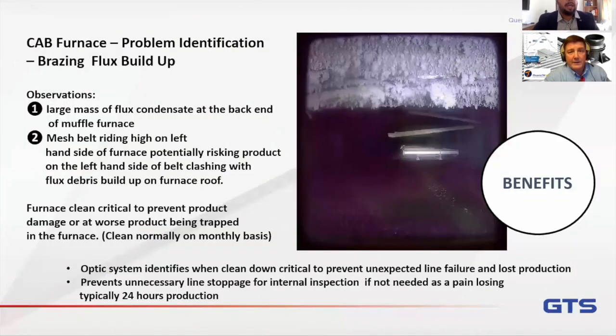Right. So I think you have a really nice example here of what kind of problems we can solve proactively if we have this kind of equipment. The thing about flux buildup at the end of the furnace, like you mentioned, is very common in these environments. Sure. And unfortunately, if the flux was to build up uniformly, it would probably be fine. But it doesn't. There are going to be colder areas of the furnace, so the flux will build up preferentially in one area. So it can actually cause at points a challenge for actually getting the product through.